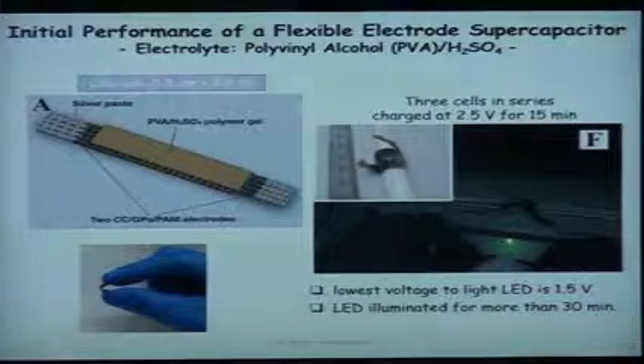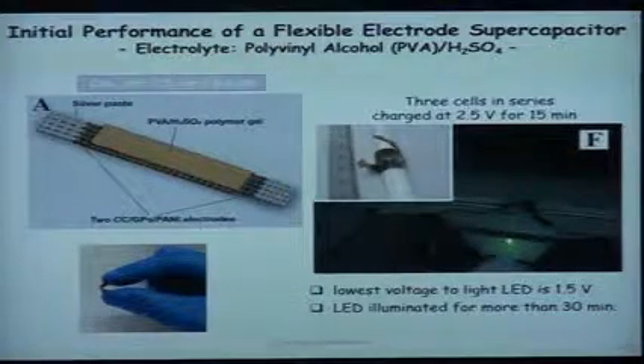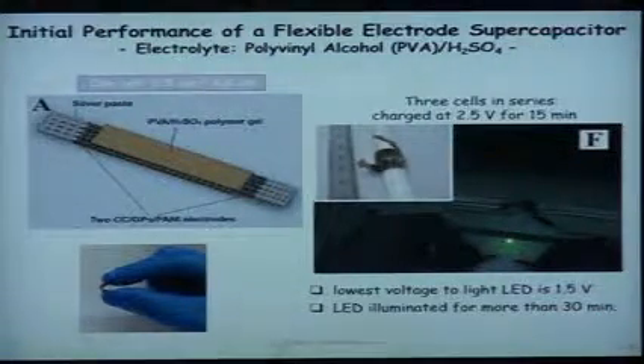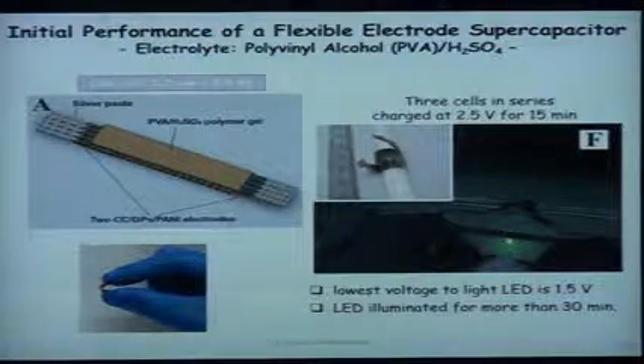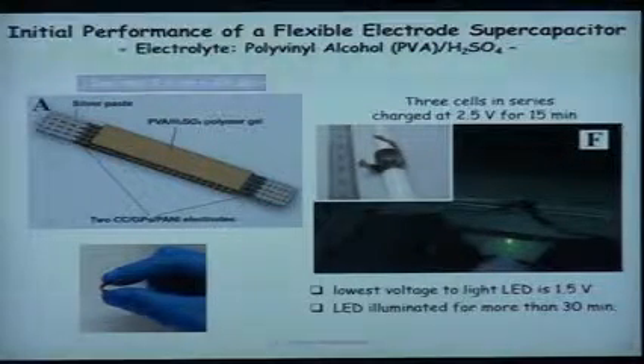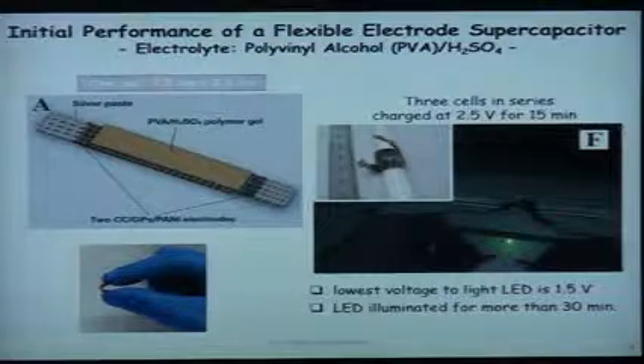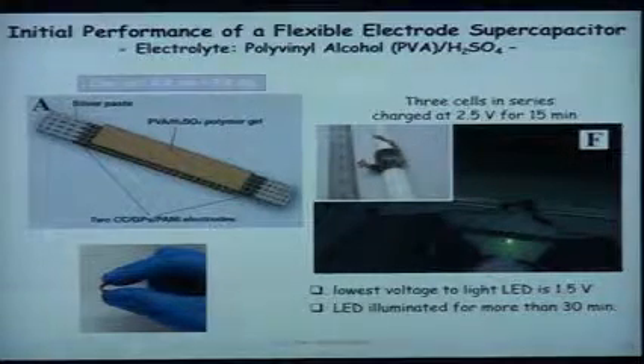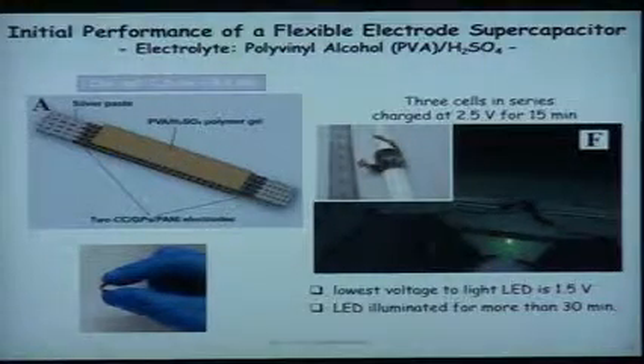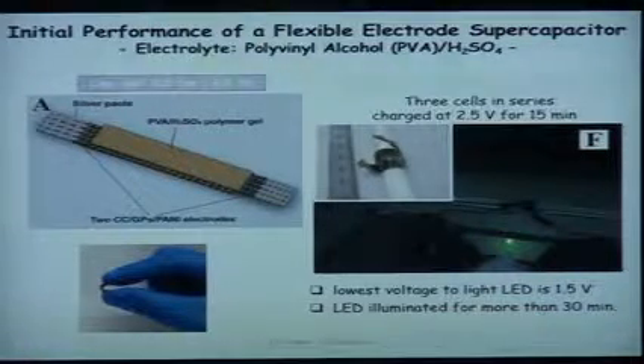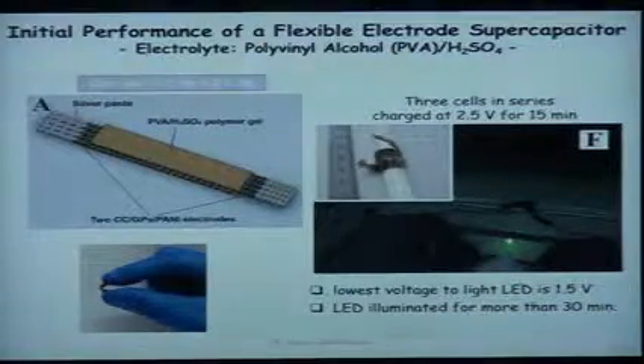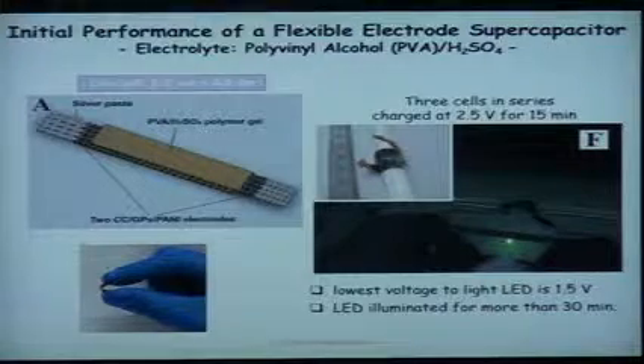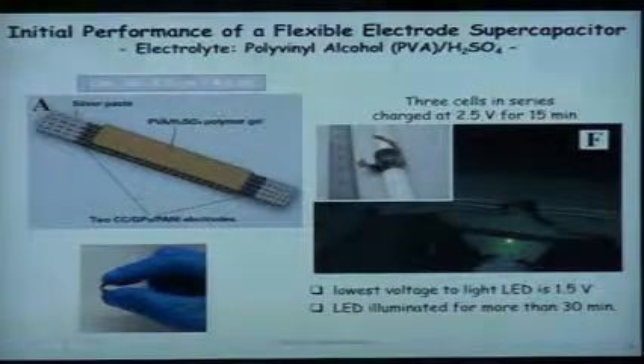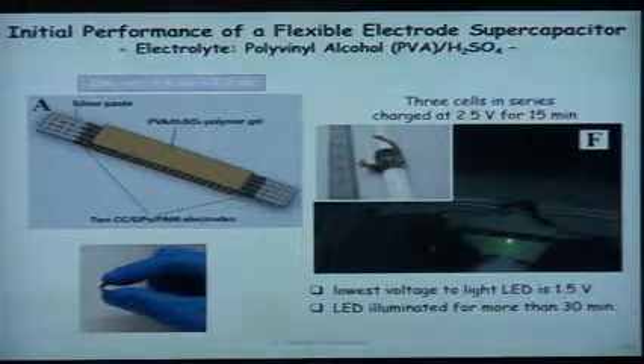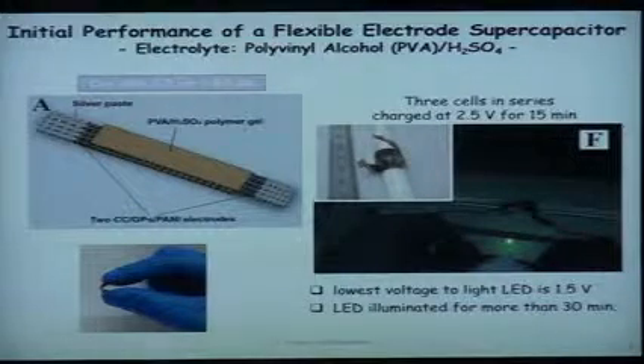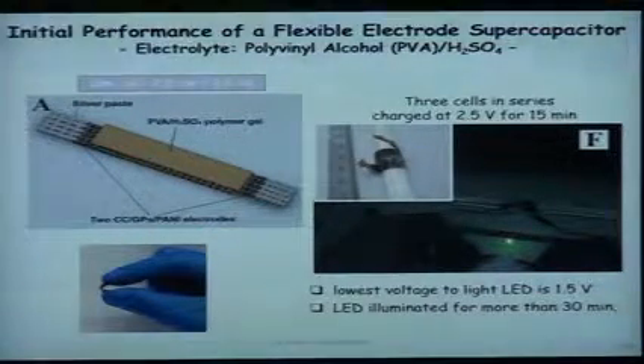And once we made it, we saw that, again, this is cloth-like. It's a layered structure. It has two sides. But we could bend it, that's shown in the bottom panel. We could wrap it around a glass rod, and we could light an LED. So this LED requires 1.5 volts in order to light, okay? And in our case, what we did is we had 3 of these cells in series in order to make a 2.5 volt device, okay?